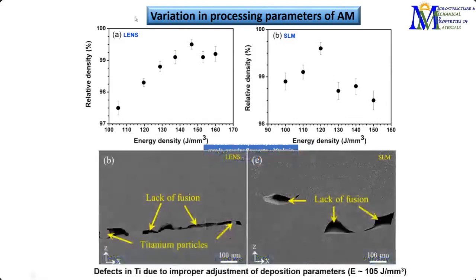What we can see here is that in case of LENS processed specimens, we can achieve maximum density, more than 99%, at an energy of around 146 joules per millimeter cube. Whereas in case of SLM, because of the differences in technique, we can achieve the same amount of relative density but with much lesser energy density.